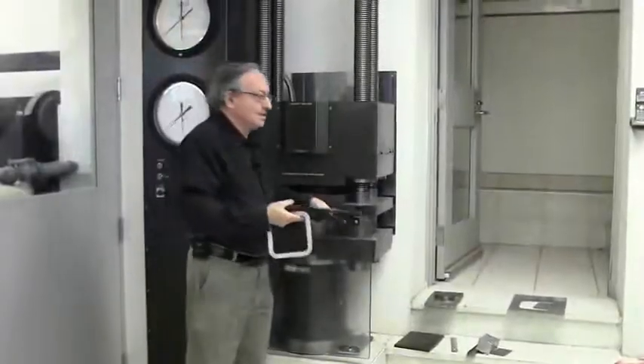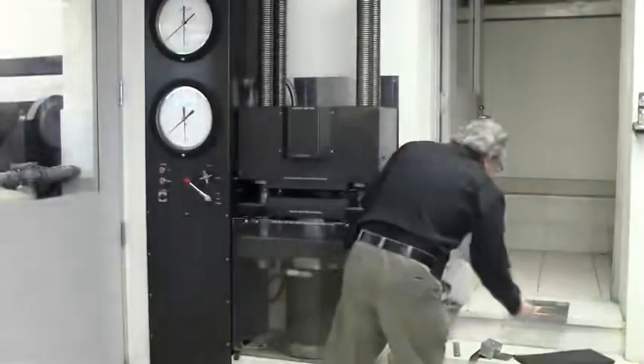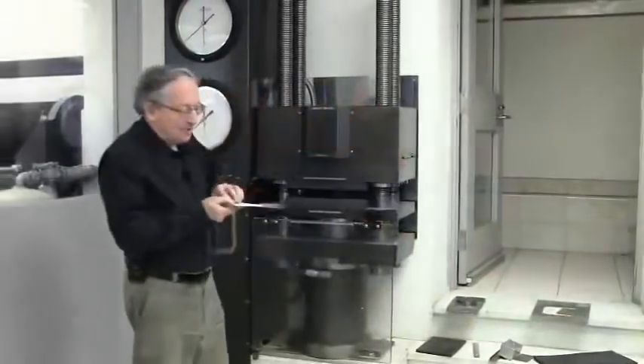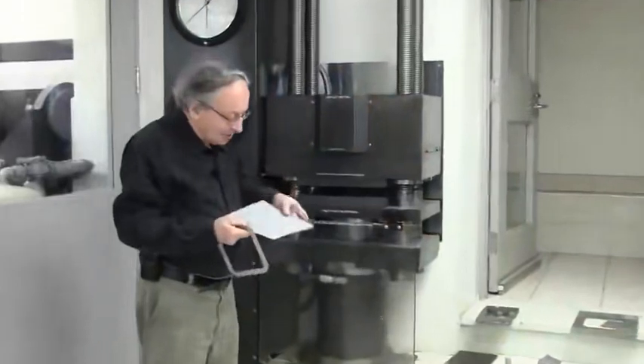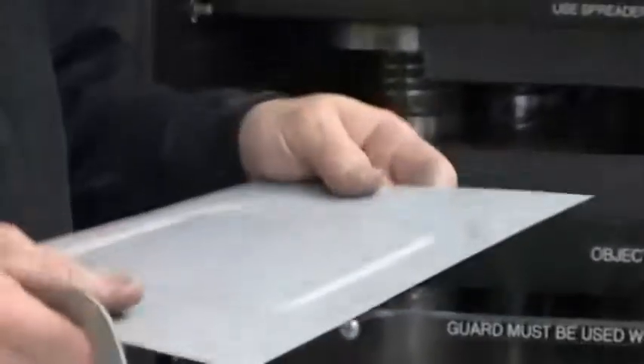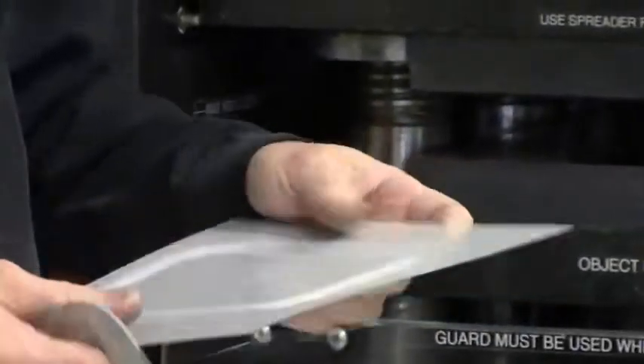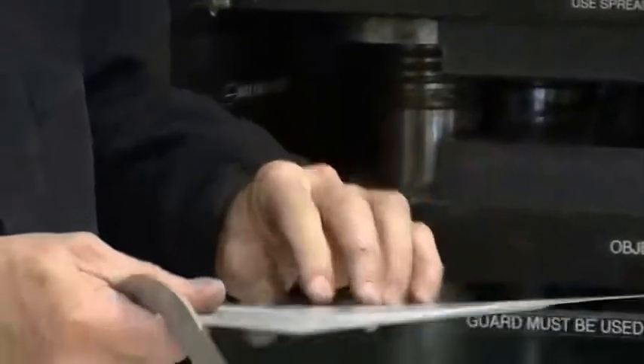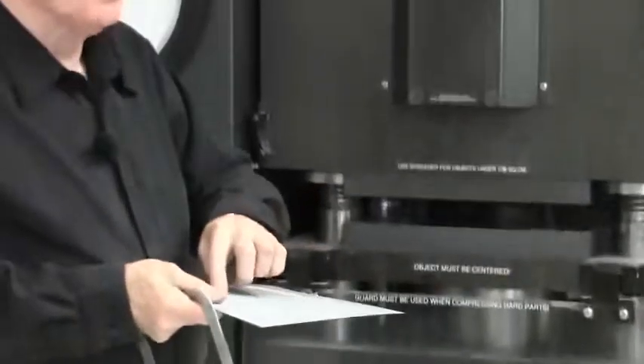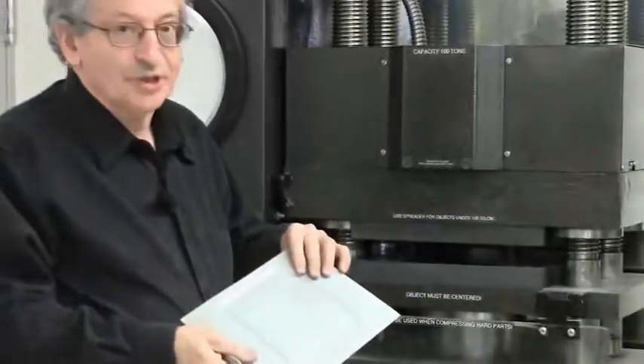Okay, so what this does, it presses a nice rib, but it doesn't have such sharp definition. So most of the time that's enough. Here it actually snaps. One reason it snaps is because the rubber was too small. It didn't cover the edges, so the edges wrinkled. The rubber has to be bigger than the metal. But anyway, it doesn't have such high definition, although this may be sufficient for a shape.